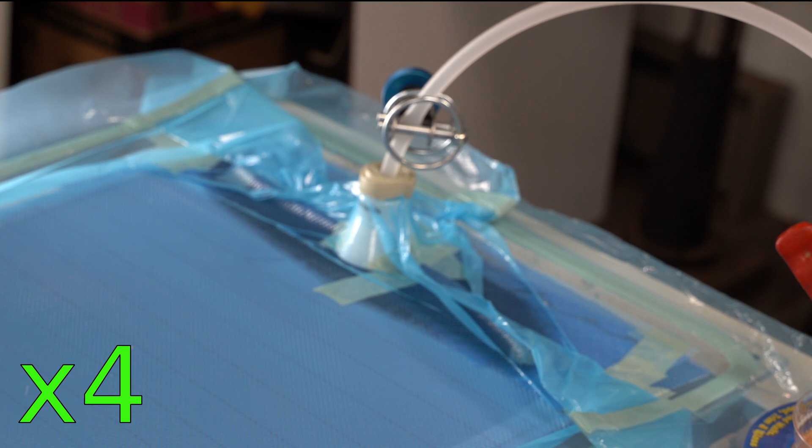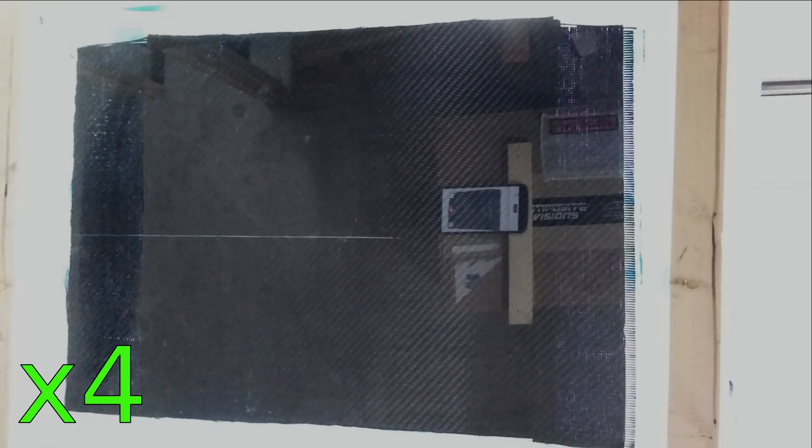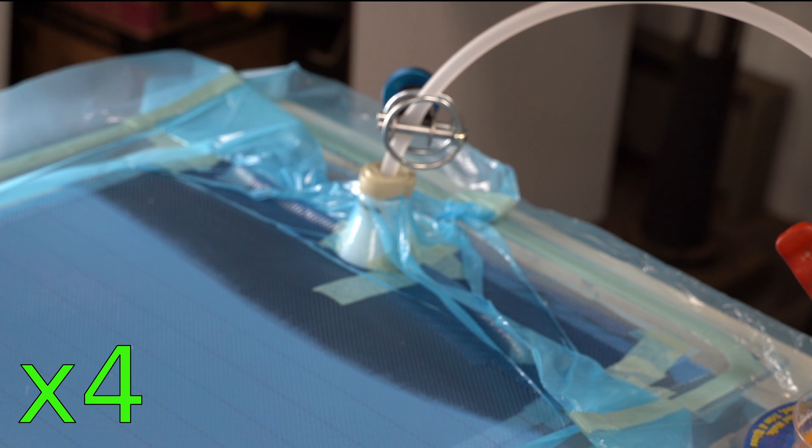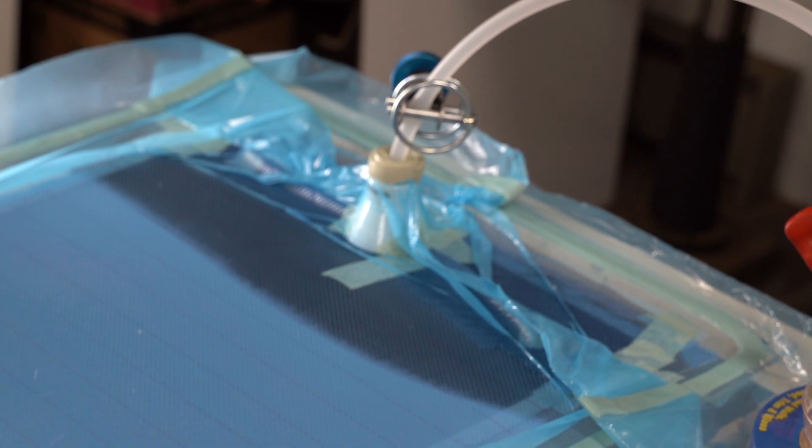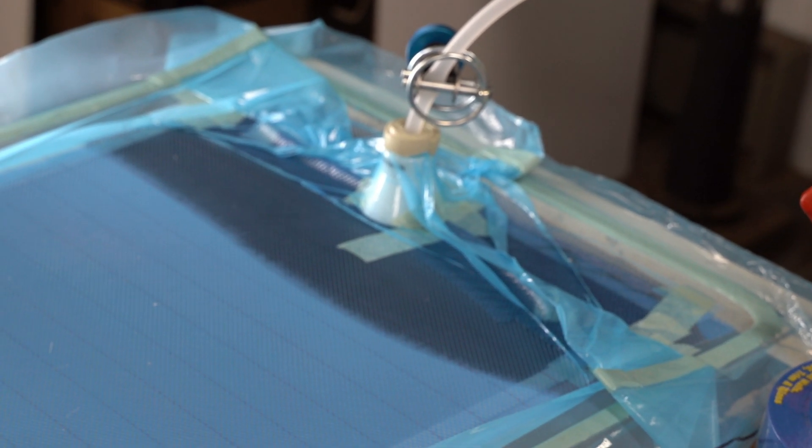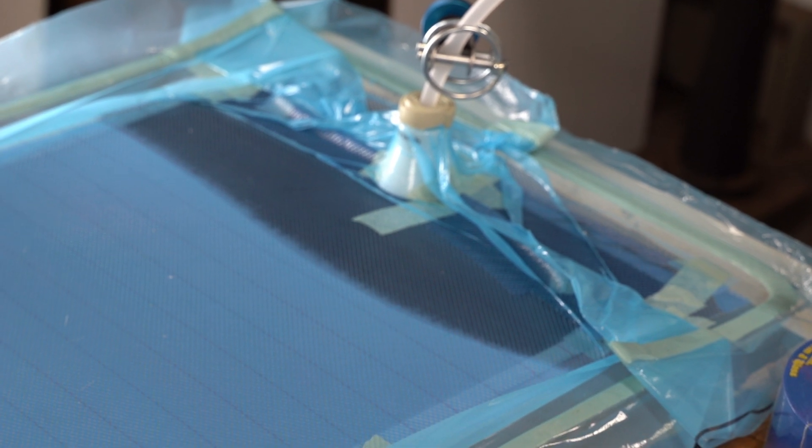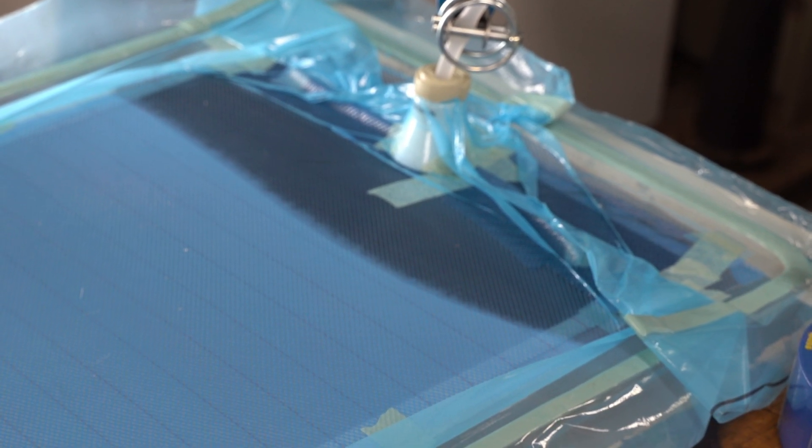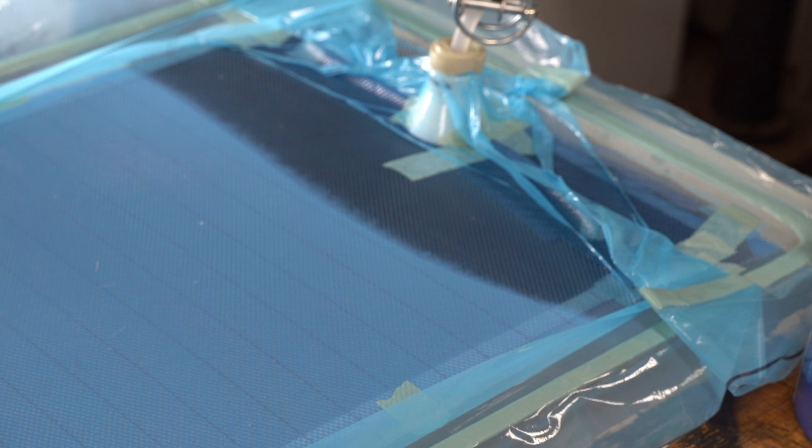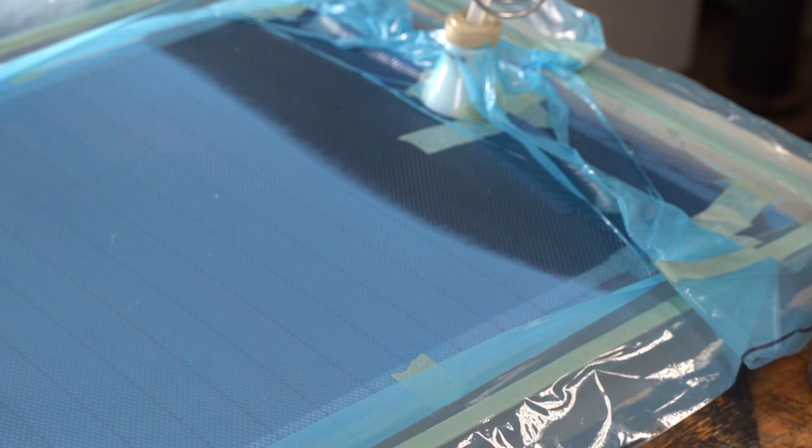And since it's taken a little while to run this I decided to speed it up a little bit. Now you can see on the bottom that epoxy has hit kind of a line there. That's where it's hitting the other layer of carbon fiber and it had a piece of masking tape on the edge when I cut it. So it's apparent that the epoxy has little trouble seeping down through that masking tape. So it's really just coming soaking in underneath it.